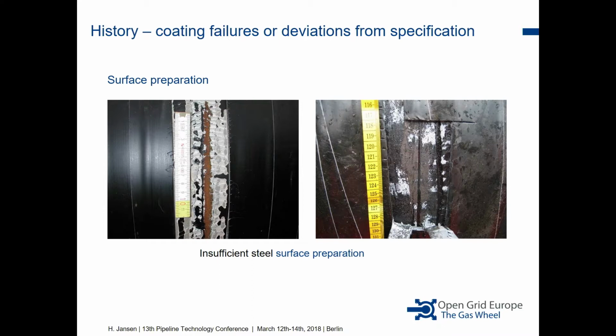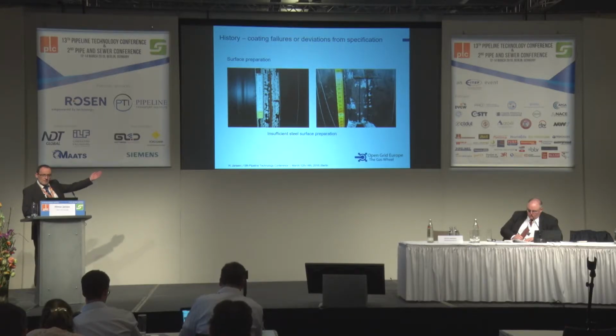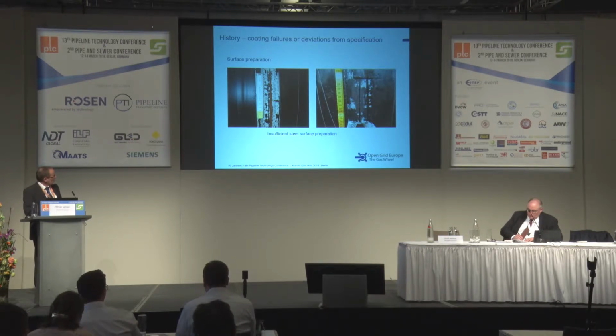Normally what we would try to achieve is a cohesive break. That means the coating system shall break within itself. What we do not try to achieve is that the coating system completely loses its adhesion from the steel surface, and you can see this in both pictures, that the entire coating system has been pulled off this surface area.